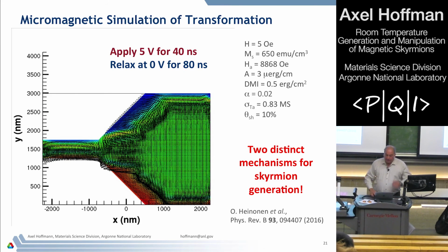When we did the simulations there, something curious happened. During the current, there was no well-defined domain structure anymore. The domain walls were completely destroyed. You got a mostly in-plane magnetization due to very strong spin-orbit torques. But then when we switched off the current, out of this mess, you still start condensing these skyrmion bubbles and individual bubbles here. There's one that gets eliminated at the edge, but here's a very high energetic one in the center that is very active for quite some time.